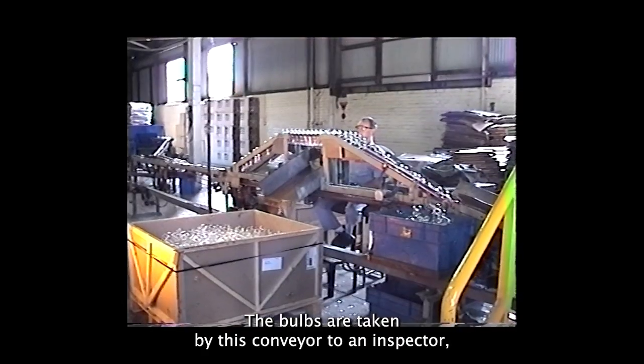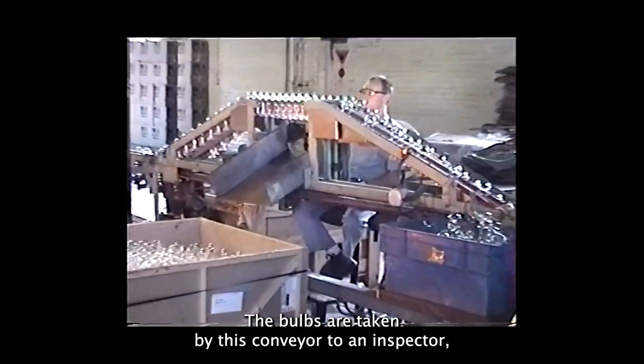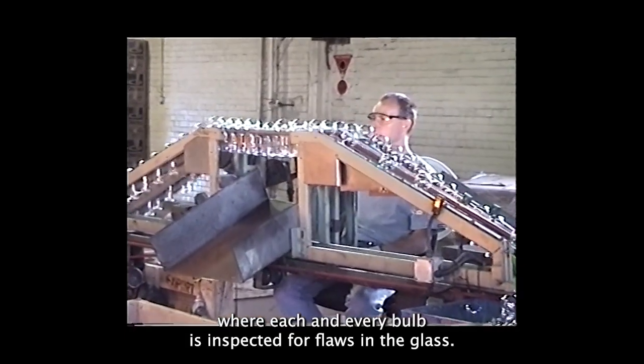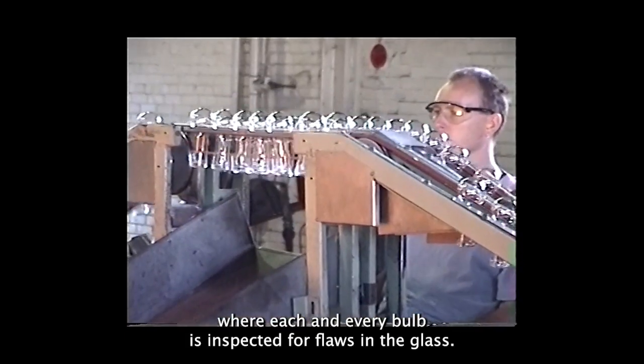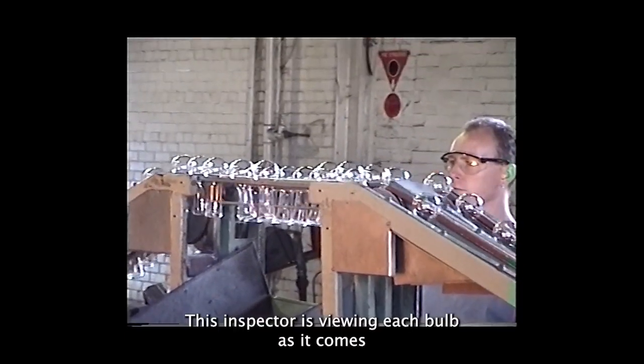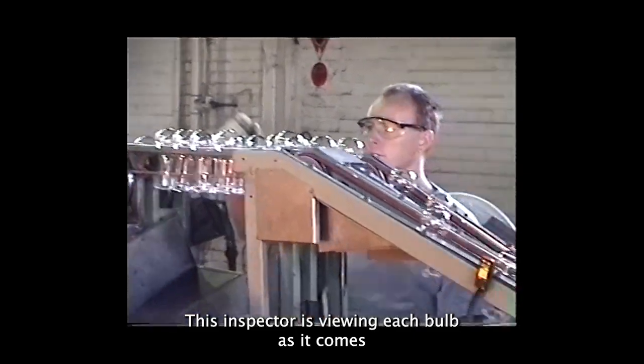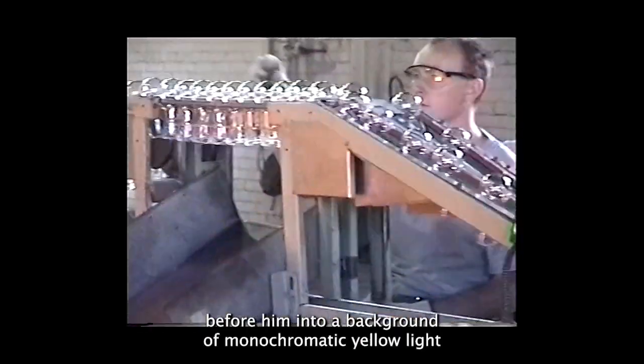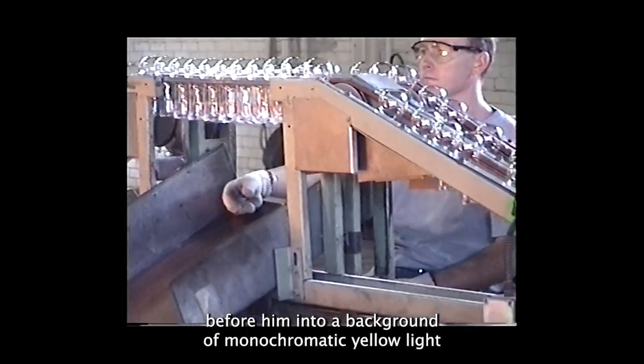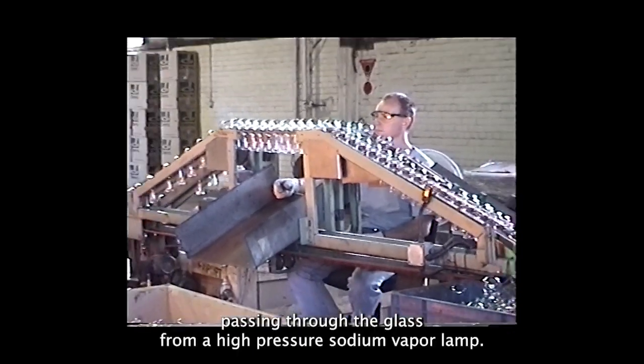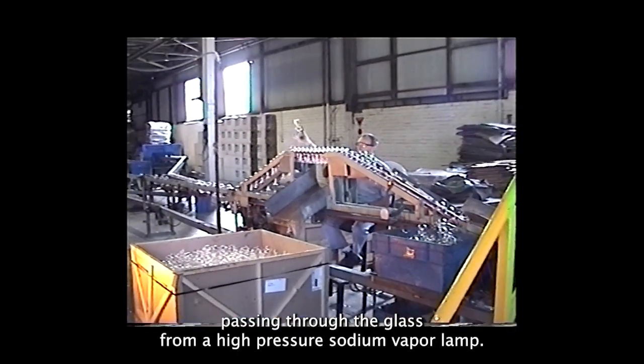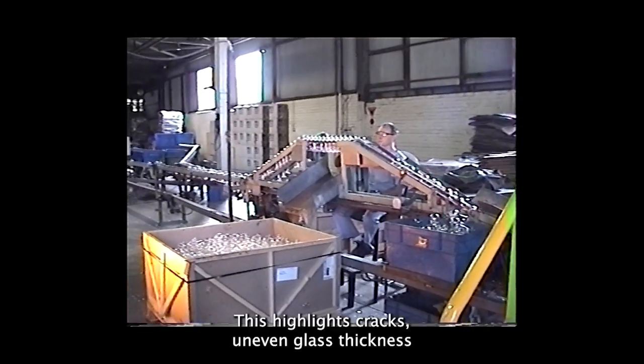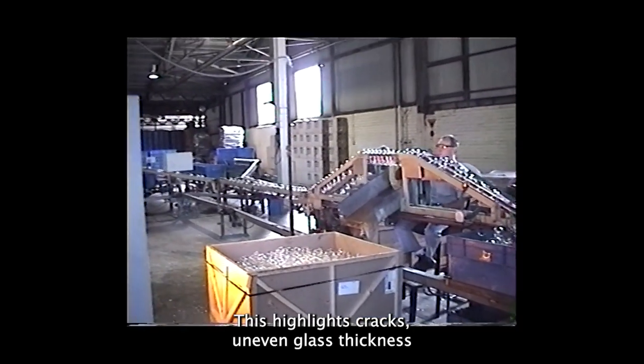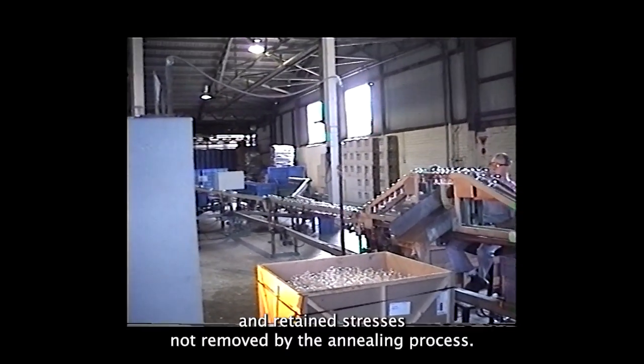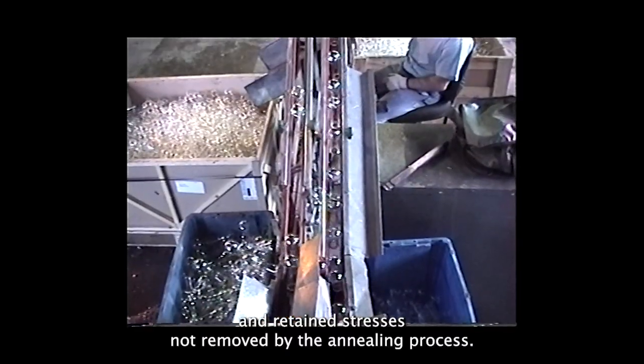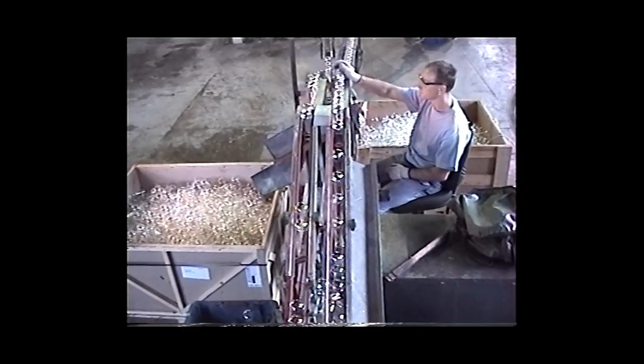The bulbs are taken by this conveyor to an inspector, where each and every bulb is inspected for flaws in the glass. This inspector is viewing each bulb as it comes before him into a background of monochromatic yellow light, passing through the glass from a high-pressure sodium vapour lamp. This highlights cracks, uneven glass thickness, and retained stresses not removed by the annealing process.